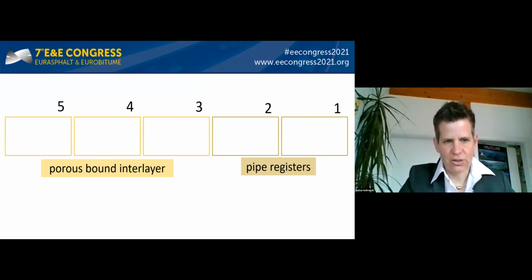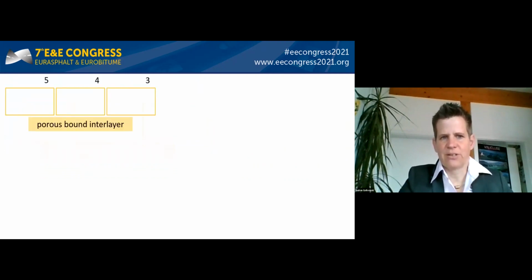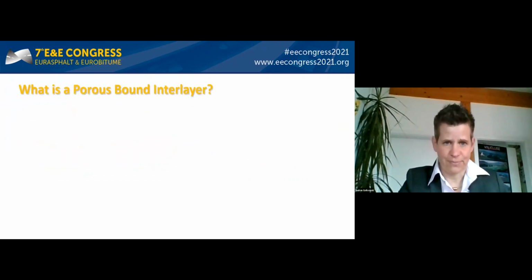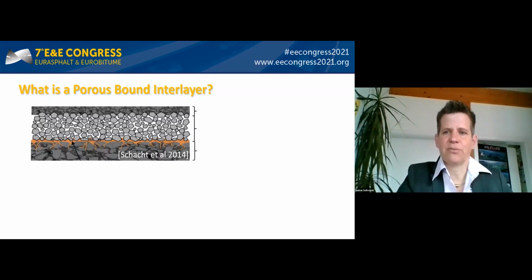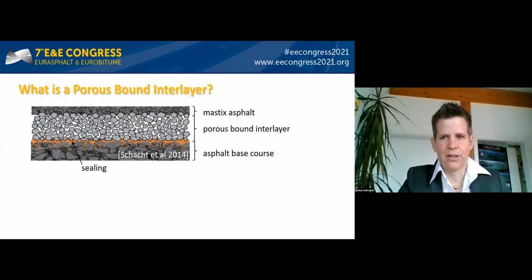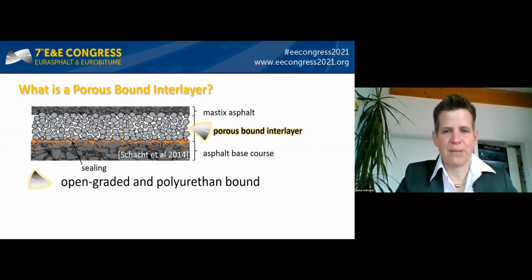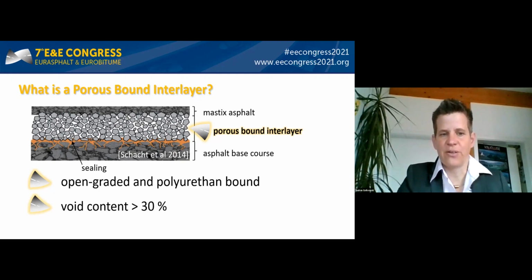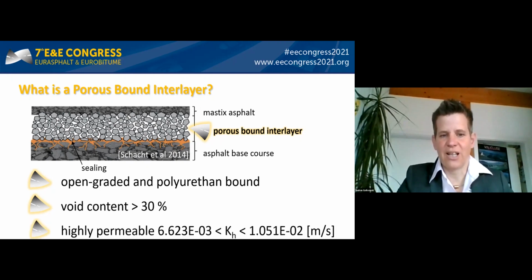And the other 3 sections will be equipped with our innovative porous bound interlayer. But what is a porous bound interlayer? The porous bound interlayer is placed on the asphalt base course, and it is covered by a mastic asphalt course. The characteristics are: it is open graded and polyurethane bound. So we don't use any bitumen because bitumen is highly sensitive to air and water. And the structure of this porous bound interlayer has a very high void content of over 30%. And furthermore, it's highly permeable.